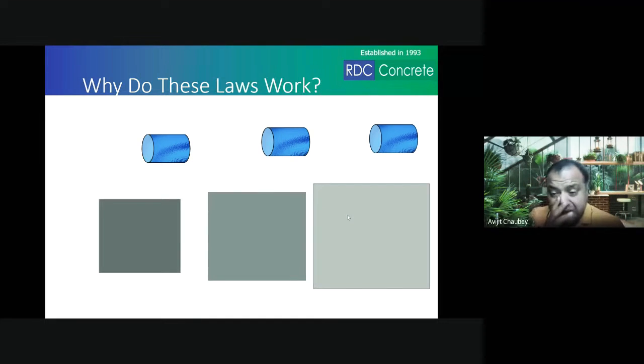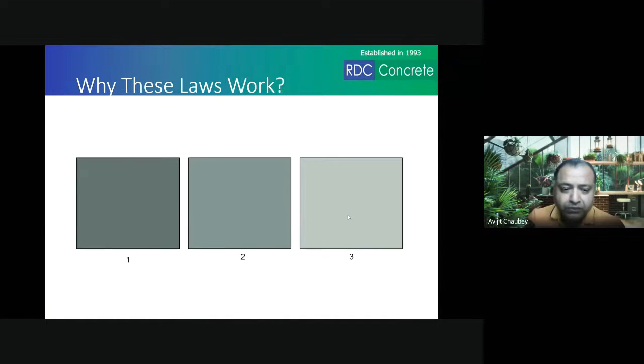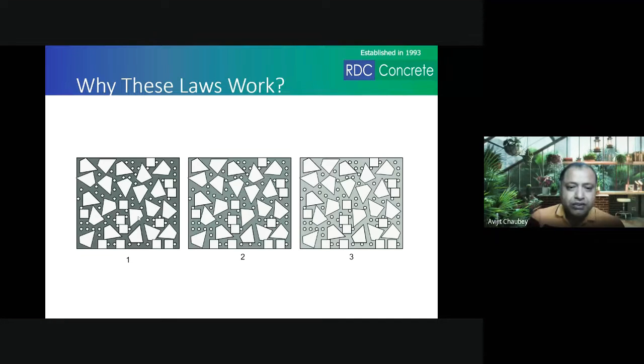And if you see mathematically, per unit volume of all these three materials, the water content would be highest in number three. Water content would be highest, and the clay material or the strength giving material, the solid material, would be the lowest in number three. And the exactly opposite would be number one, where the cement or the clay content would be the highest and the water content would be the lowest. So this would be a stiffer kind of a mix, and when it dries up, this would give you a higher strength, right?